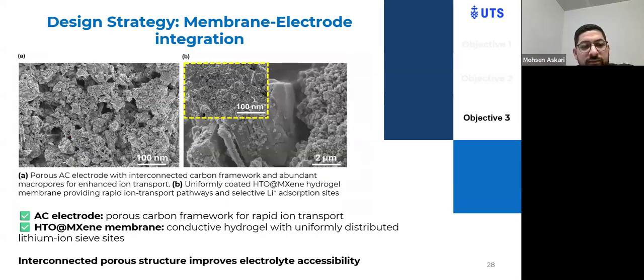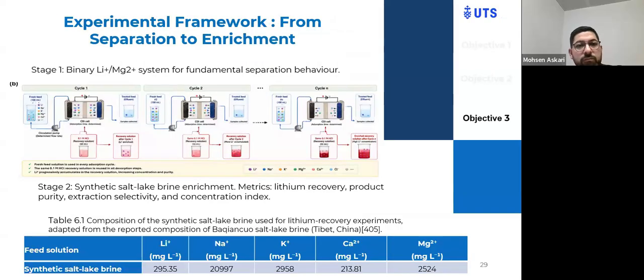The SEM shows the AC (activated carbon) electrode has a porous carbon framework for rapid ion transport, and the HTO@MXene membrane has a conductive hydrogel with uniformly distributed lithium ion sites and MXene. The interconnected porous structures are expected to improve electrolyte accessibility and performance.